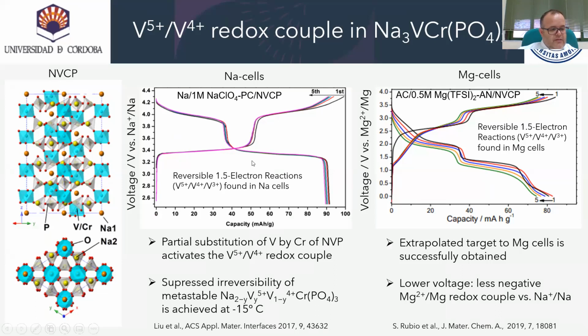In sodium cells, NVCP exhibited a galvanostatic curve with a 2-step plateau at 3.4 and 4 volts with around 90 mAh per gram of capacity, exhibiting a 1.5 electron reaction due to the vanadium 5, 4, and 3 redox couple.